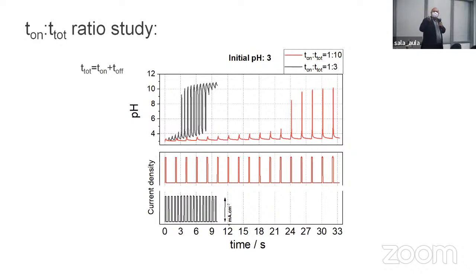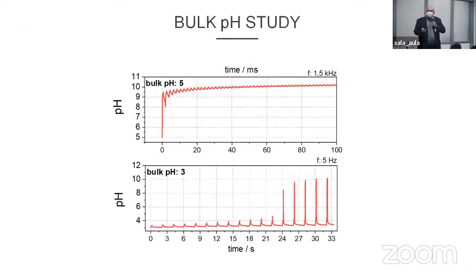And for sure, I told you, this is simulation data. And then for sure, we start to investigate this using experimental data. They are very simple to perform in an electrochemical cell. But until now, we can't find a situation where even this spike here does not occur experimentally. And I think this is very important because besides the electrode stability, there is an energy loss when you have this pH transition. You have an increase in the overpotential of the cell due to the interfacial pH change.